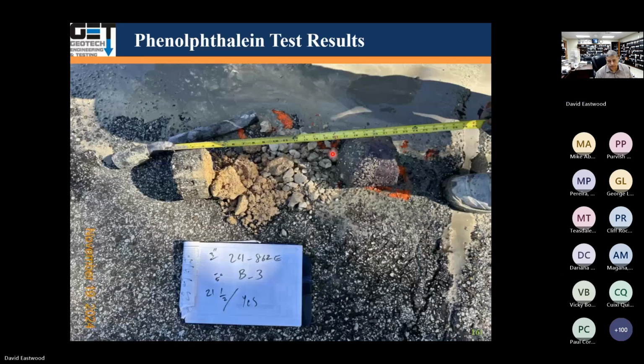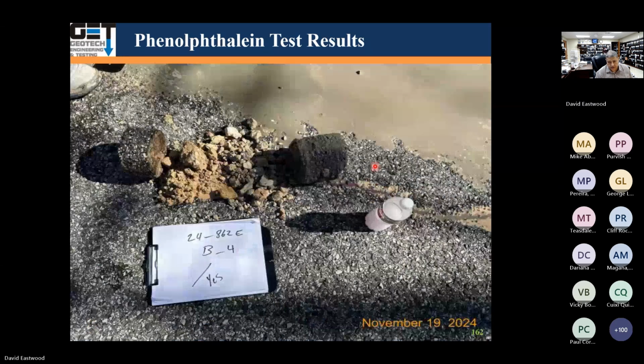Okay. Again, you can see in here, asphalt, base, stabilized. Verify that there was some lime stabilized subgrade or cement stabilized. In this case, since the soils were fat clays, we assumed this thing to be lime stabilized. And you can see here the asphalt, the base, this is a stabilized layer. It's got a little bit of purple in it.